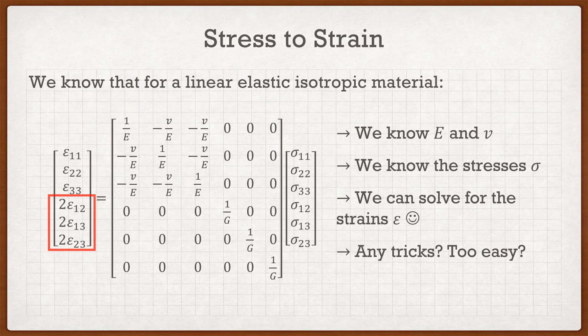Keep in mind that when we're finding the eigenvectors and eigenvalues of a tensor, we need a tensor. And when we find these strains, we're given a strain vector. So what we're going to have to do is take the strain vector and fill out our strain tensor. Now the problem is all of these shear strains are actually 2 times whatever the actual strain is. However, students won't realize that, so if they get the entry in this vector as, let's say, 0.5, they will enter 0.5 directly into the tensor.